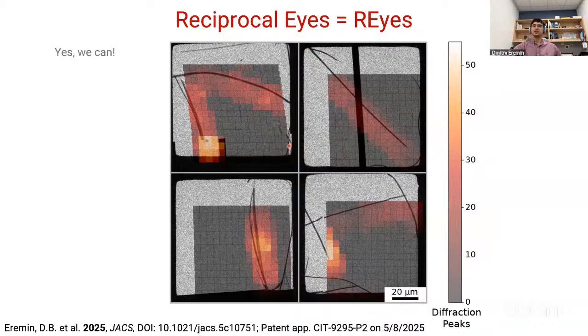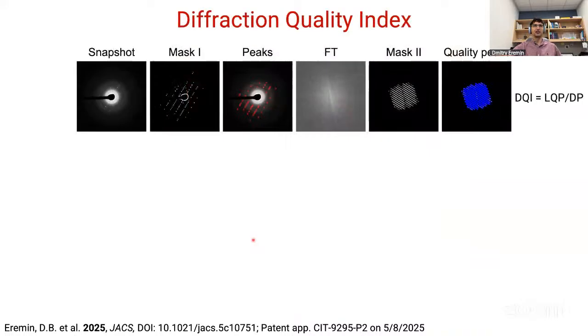We are intentionally not using any selected area aperture in any of these acquisitions, because when software completely autonomously collects the data, you don't know exactly what is going to overlap with your target. It might be the grid bar, it might even be another crystal as in here. So what you want is a nice, clean, single crystal pattern. And if you don't have a selected area aperture, you have a wide enough range around your target where you will know that even if you tilt it, you're going to collect good enough data.